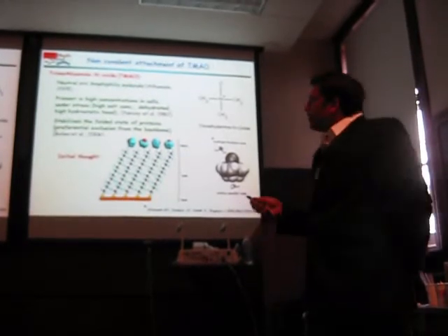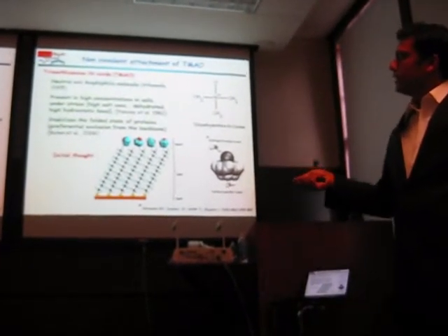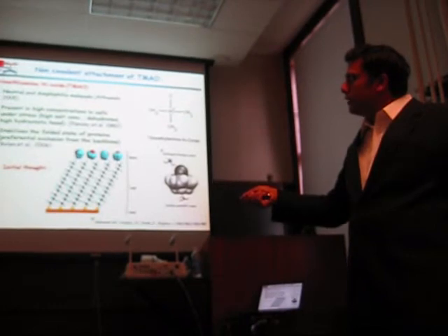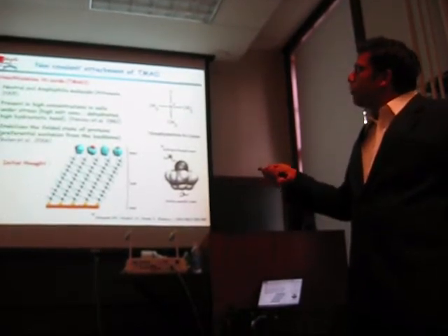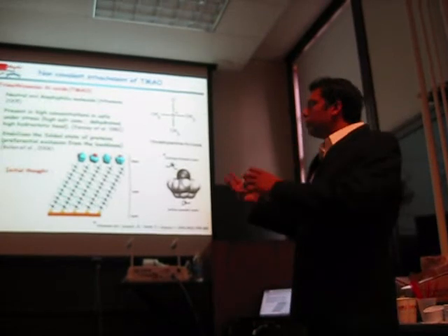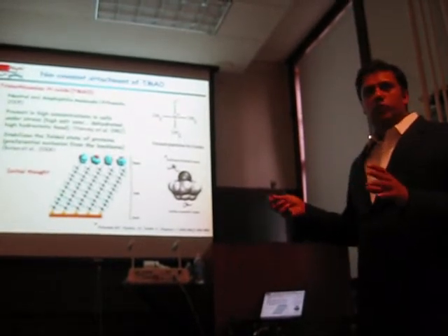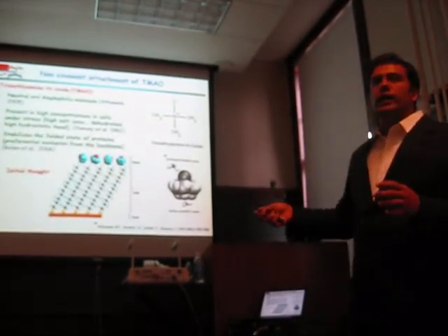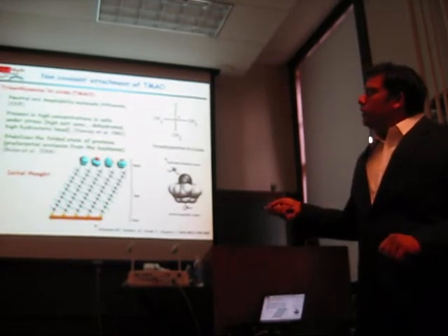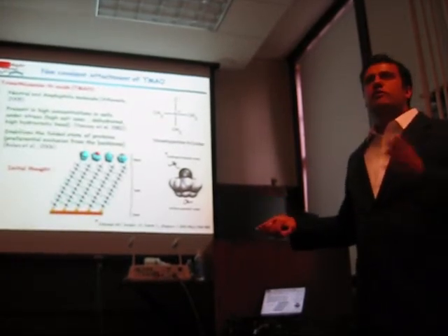What we thought is that hydrophobic substrates are notorious for protein adsorption. So this is the schematic: this is the CH3 SAM, the ball model, and these are the CH3 groups on the top. These are alkanethiol SAMs, this is the gold substrate, and these are sulfur atoms. We thought that the hydrophobic end of the TMAO molecule can be utilized to self-assemble on the hydrophobic surface. Because the length scale of this molecule and the CH3 groups on the top is equivalent, it can also bury itself into the interstitial spaces. That was the initial idea: we can have all the O's pointing upwards and make the surface hydrophilic, and since these hydrophobic interactions are small, we can remove it off.